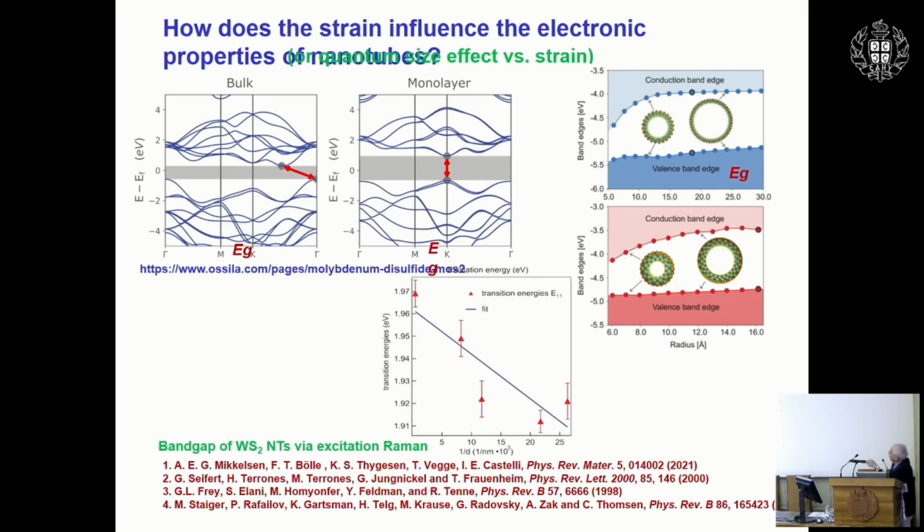You know very well that when you take tungsten disulfide, it's an indirect band gap transition of about 1.4 electron volt. And when you exfoliate it into a single layer, owing to the quantum size effect, you get a direct transition, which is much larger, about 2 electron volt or 2.5 electron volt, compared to the multilayer tungsten disulfide or molybdenum disulfide, for that sake.